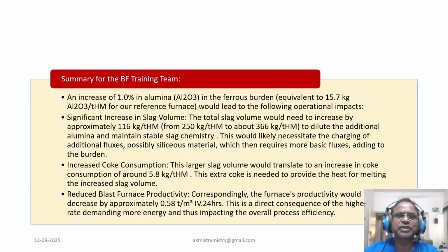So a small change in burden chemistry leads to significant operational penalties, and this example reveals a crucial insight: even a minor shift in raw material composition can drastically increase cost due to the increase in coke rate, and reduce output as productivity goes down, and it destabilizes the process also. Higher coke rates mean more fuel expense, lower productivity means less hot metal, and unstable slag chemistry risks tapping delay and refractory damage also.